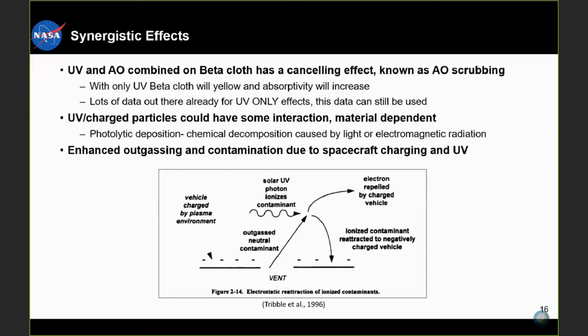There's lots of data out there already for UV-only effects, so this can still be used, but you do have to make sure that in your test, or in whatever research you're looking at, the absorptivity was measured in vacuum to make sure that there was no oxygen exposure. Then there's also UV and charged particles. They can have some interaction. It's material dependent. It's called photolytic deposition, which is a kind of chemical decomposition caused by light or electromagnetic radiation. And then there's also the effect of enhanced outgassing and contamination due to spacecraft charging and UV.